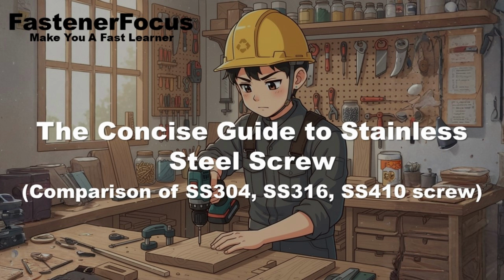Absolutely. 410 is the dominant material for self-drilling fasteners, commonly known as Tek screws. For a screw to be able to cut its own hole, tap its own threads, and fasten the material in one single operation, the drill point must be significantly harder than the steel it is penetrating. The 410 grade achieves this by being quenched and tempered to a very high level of hardness, often exceeding 50 HRC, that's the Rockwell C scale, at the tip.